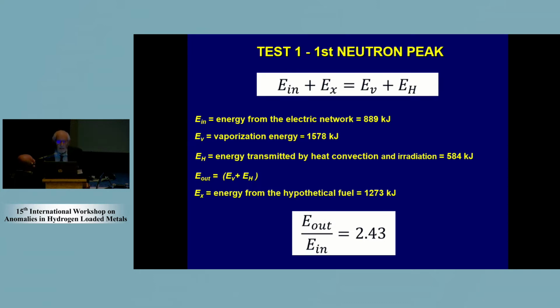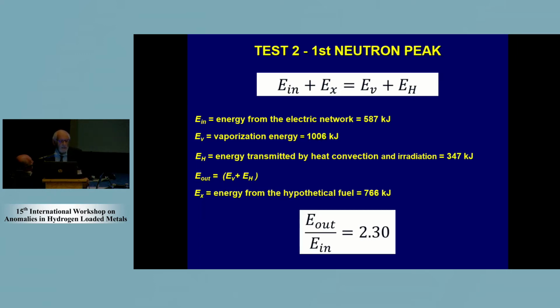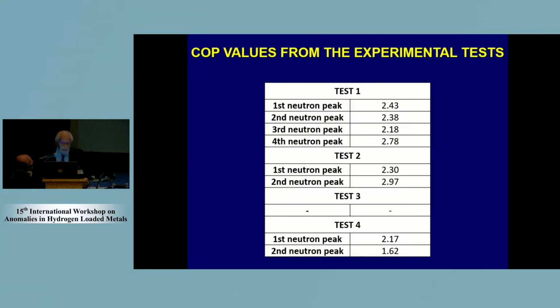In this case, I repeat, limited to these segments or time periods, it is more than 2, you see, 2.43. Then we perform the same calculation for the second peak, the third peak, and fourth peak of the first test, and the other peaks of the second, third, and fourth tests. I give you the final results in the table, but it's a very simple calculation, it's repeatable, and we have this series of values.